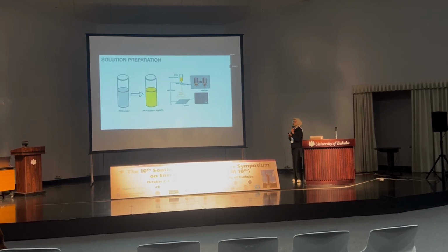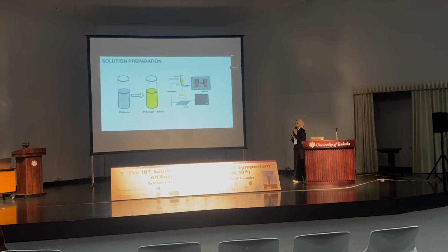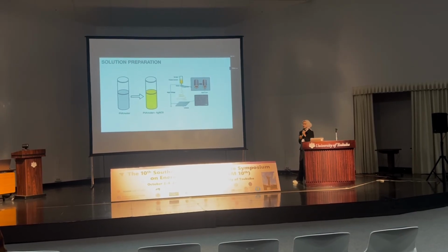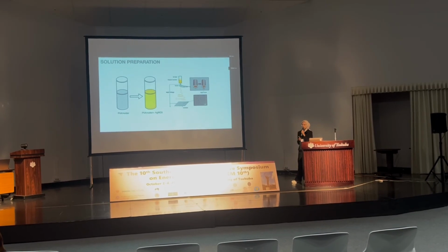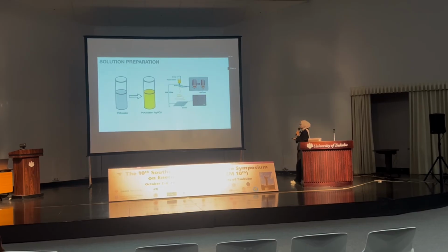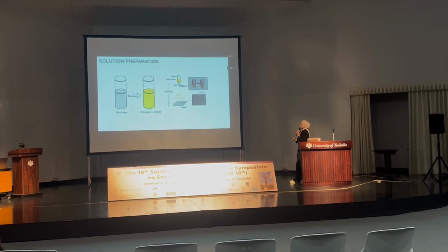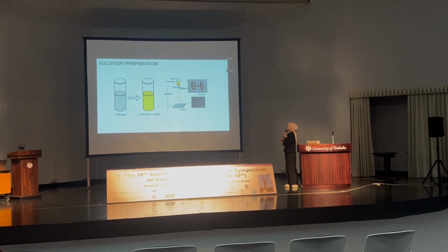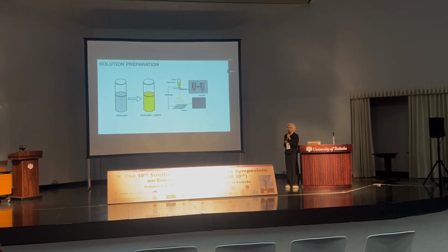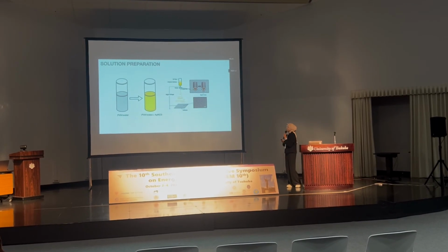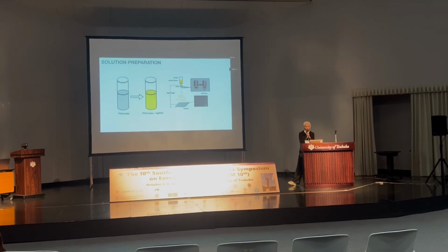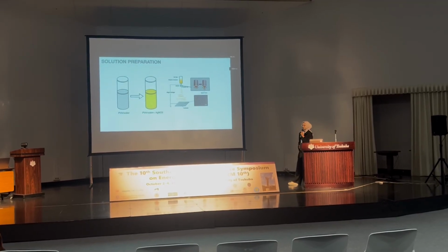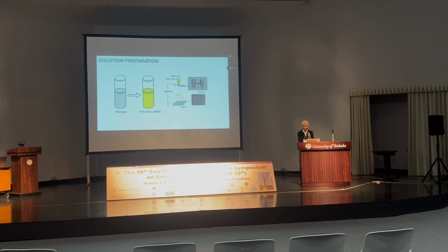After the PVA solution is prepared, I fabricate the PVA nanofiber by varying the spinning parameters, such as the feed rate, concentration of solution, the voltage, and the distance between the tip of the needle and collector. In addition, to expand the work, I add the antibacterial agent silver nitrate to create the antibacterial nanofiber with different concentrations of the antibacterial agent.